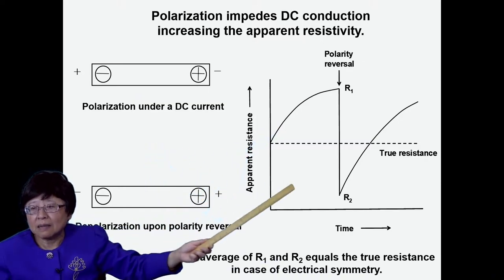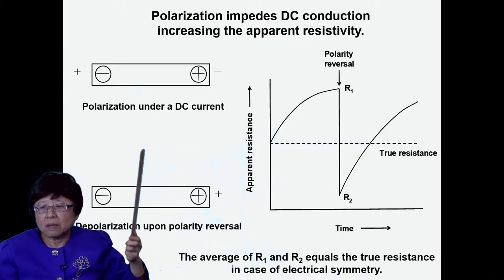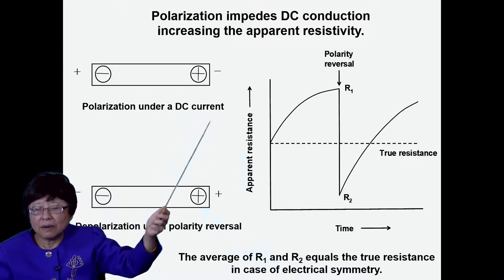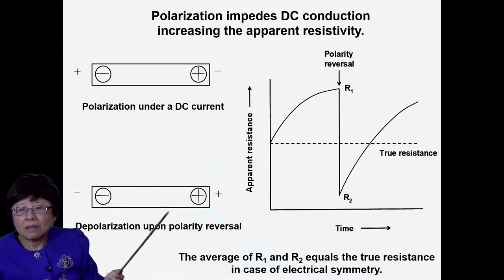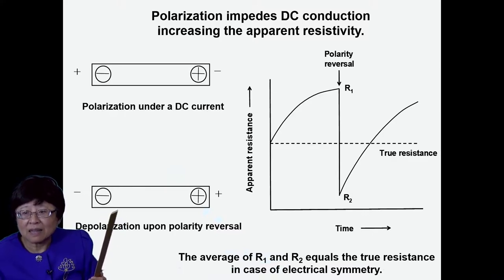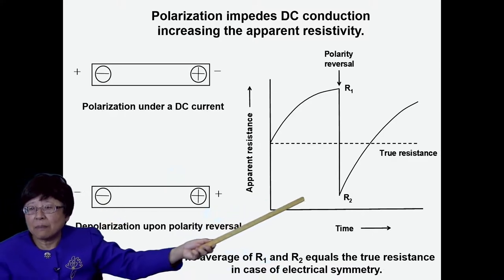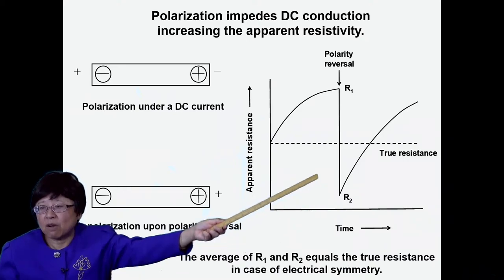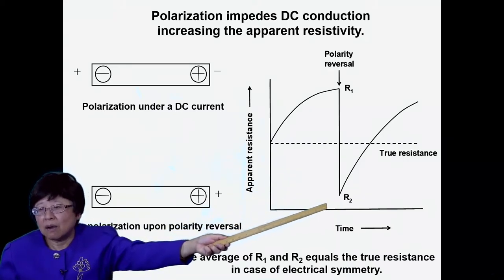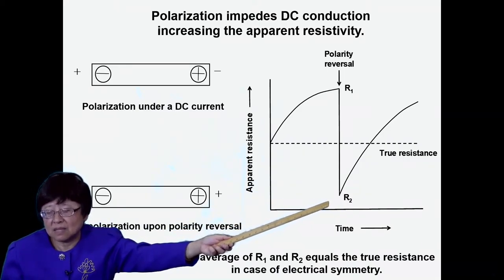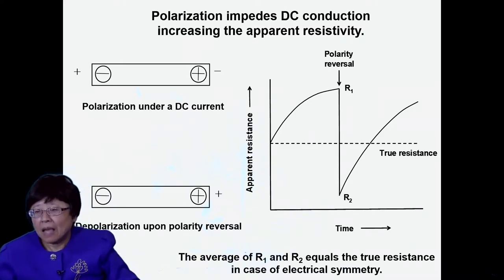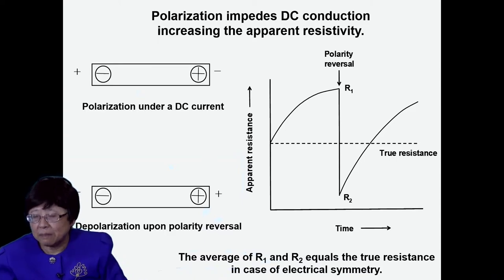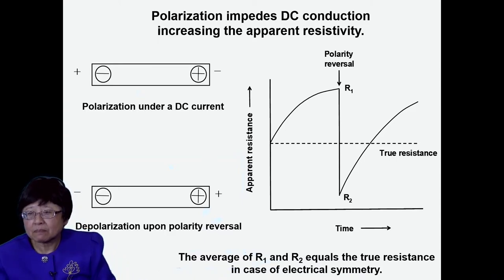And if you suddenly reverse the polarity of the applied current, then this dipole becomes aiding rather than impeding the conduction. And so the apparent resistance suddenly drops from R1 to R2, and R2 is below the true resistance. And the average of R1 and R2 equals the true resistance in case of electrical symmetry in the material.